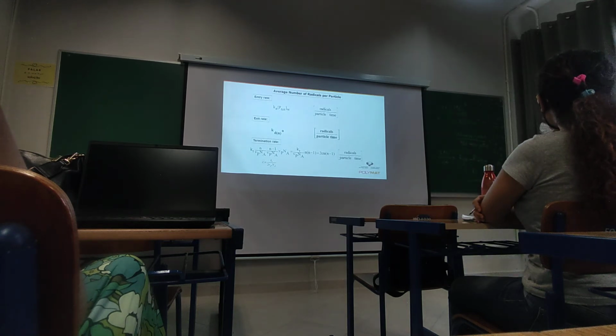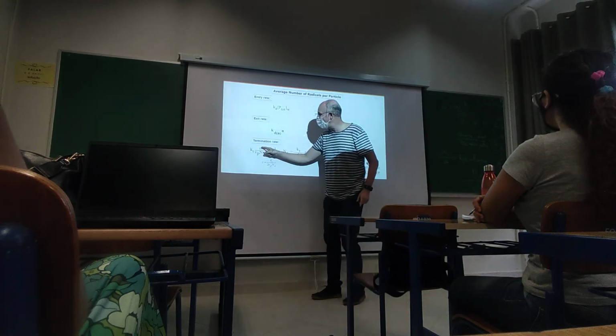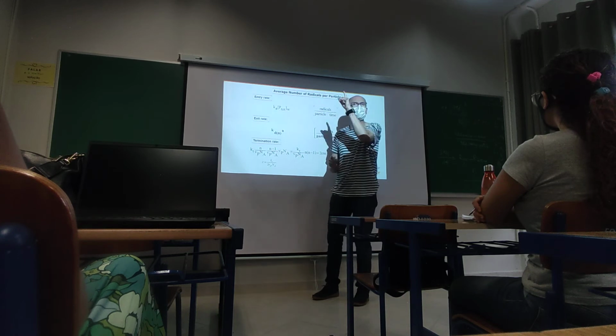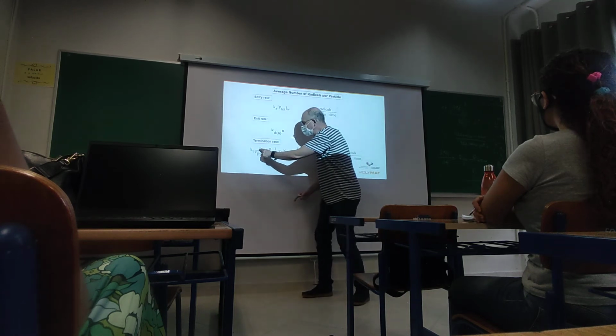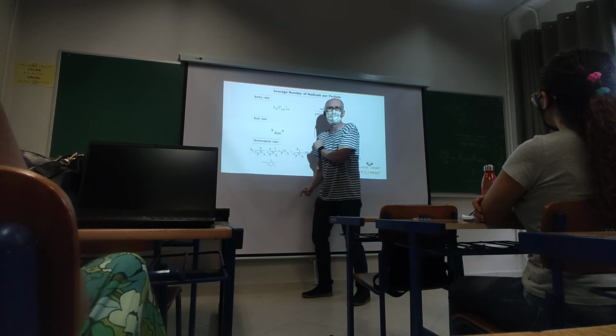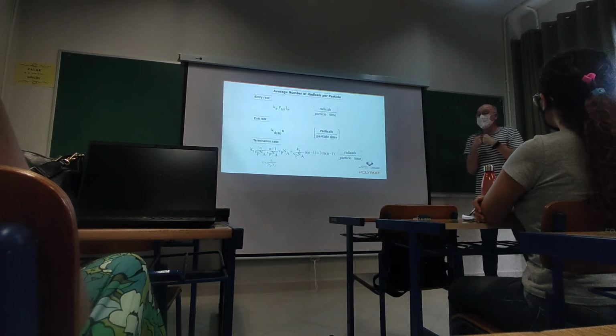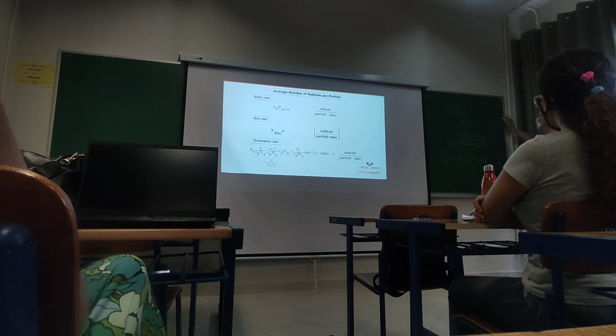So that's why when calculating this term, we have to distinguish the radicals. And that's why here you don't have n divided by Vp N A, which would be the radical concentration squared. So we distinguish n and n minus 1, because each radical cannot terminate with itself. Here, in solution, 10 to the 16 minus 1 is equal to 10 to the 16, so there is no difference.